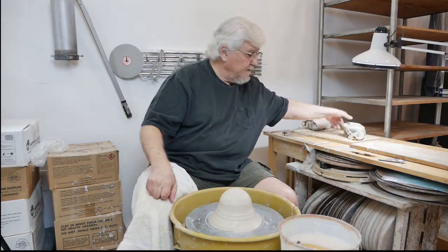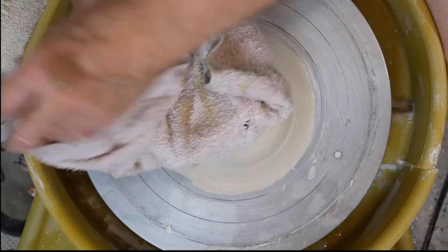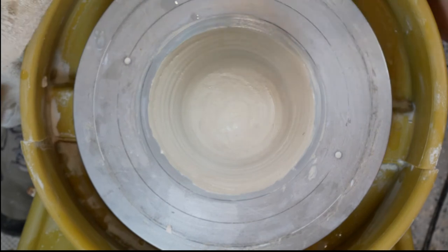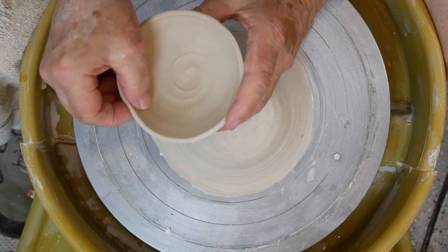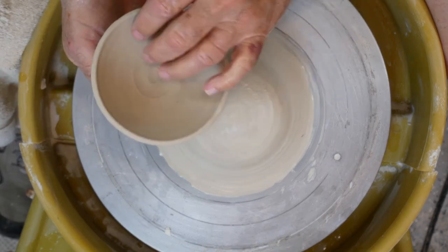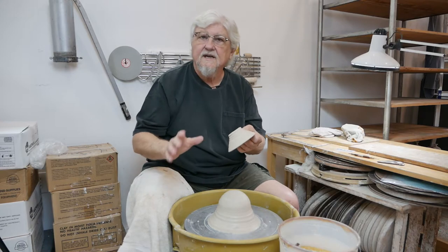This morning I did that to the brother of this piece and took it out after a couple of hours, and this is what I have. The clay has absorbed the water from the towel — check this out, it's plastic again. I can put my fingernail into it; it's ready to trim. If anything, it's a little on the soft side, so I could leave it out a bit, but I'm going to go ahead and trim it for you anyway.